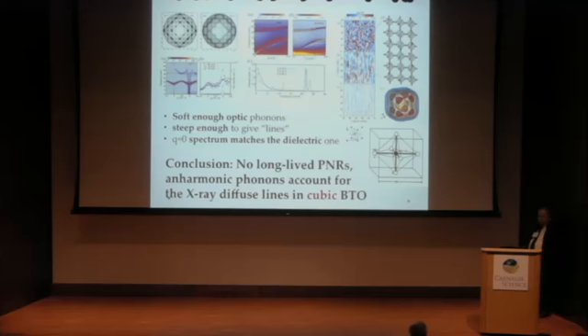To some extent, I agree with what you conclude. But for instance, if you look at the EPR and NMR data, then you clearly see that there is something like an order-disorder component present in the cubic phase, above TC. Yeah, this is the blind approach. You know that for sure. Sure, I think he mentioned as much.